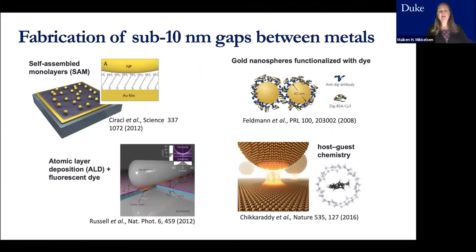Ways to do that often take advantage of chemical techniques, and instead of looking at a lateral geometry, look at a vertical geometry that allows you to leverage layer by layer deposition methods. Ways to achieve such small gaps in a controllable manner include self-assembled monolayers. You can also take advantage of atomic layer deposition, and in this case silver nanowires, functionalized gold spheres here with dyes, utilizing host-guest chemistry that also allows you to position molecules underneath. So we can see we have some ways of moving to these very small dimensions, but it requires us to think a little bit outside the box and not use our traditional electron beam lithography techniques that a lot of people from the physics community are starting out with.